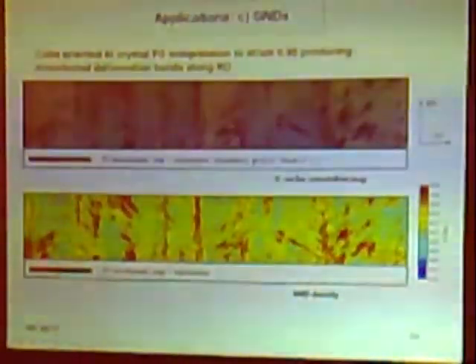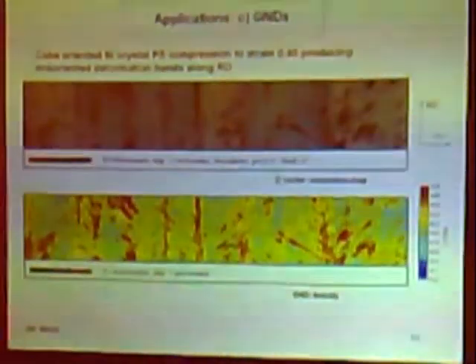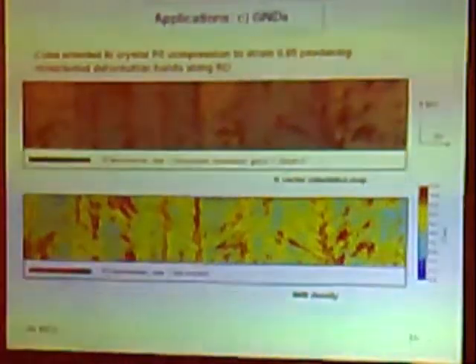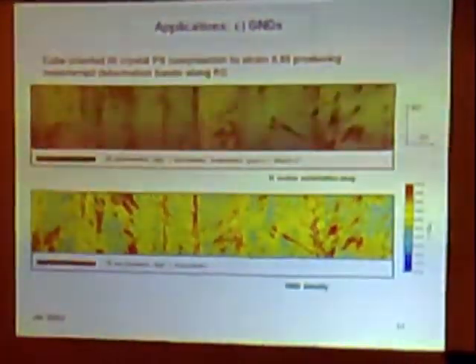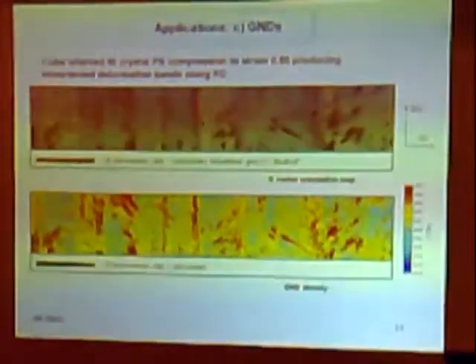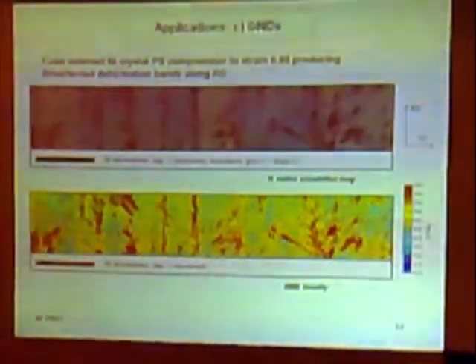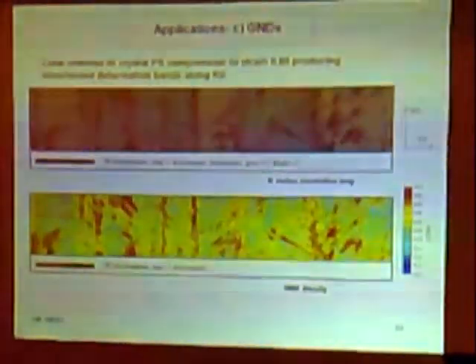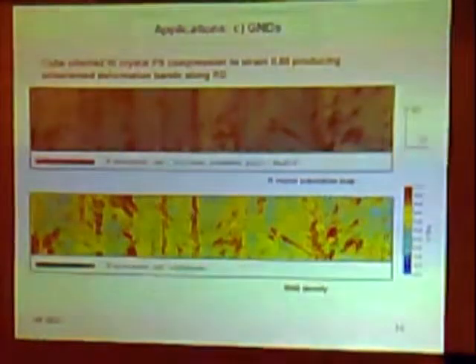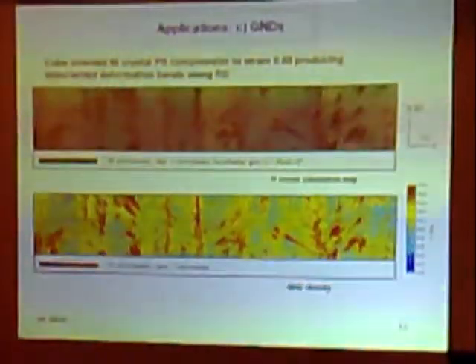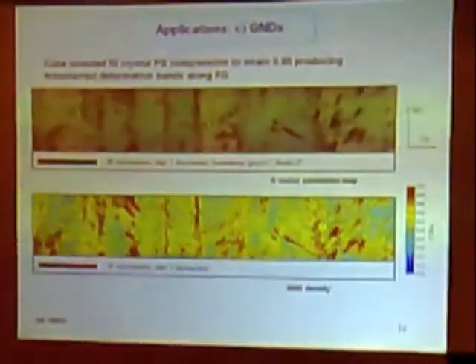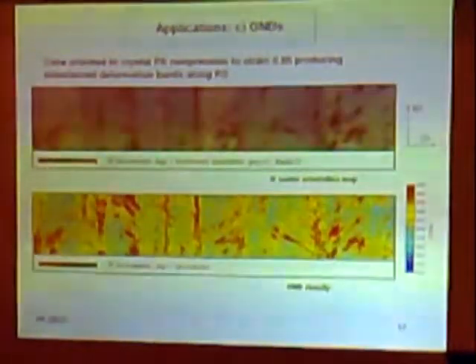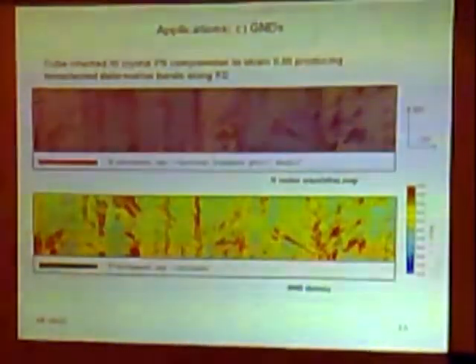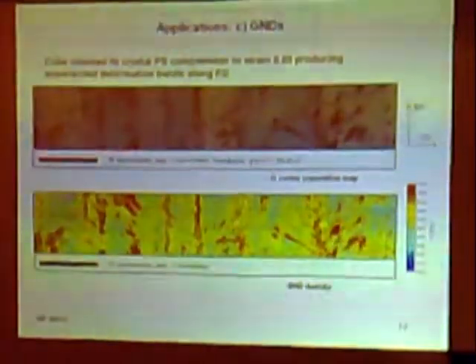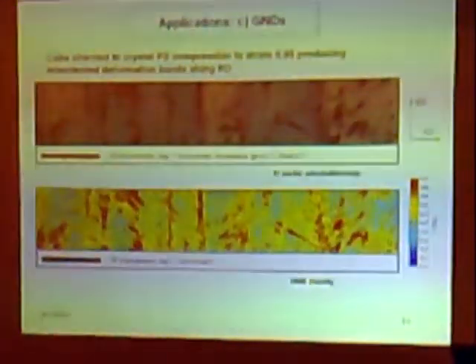And this gives you a map of a cube-oriented nickel crystal, which is plane strain compressed to a strain of 0.85, and produces misorientation deformation bands along RD. RD is here. So this is a Rodrigues vector orientation map, so you can see you're developing large orientation gradients and transition bands. And the transition bands are accommodated by GNDs. And using this analysis that I just very briefly described, you can calculate the local GND density, and this shows the GND density on the same area.